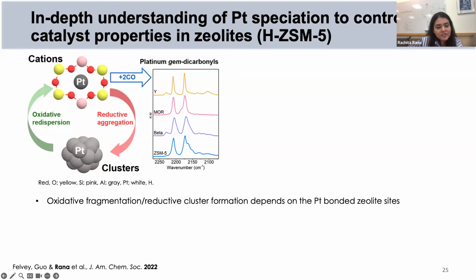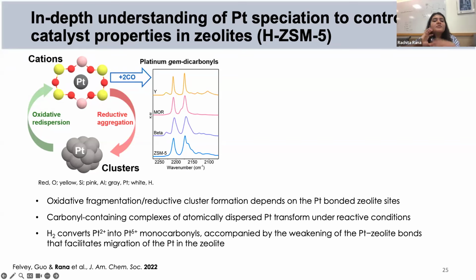Noah, his PhD student then, where they were trying to understand the speciation of platinum, where it would redisperse under oxidative conditions. And then when you reduce it, it would become a platinum cluster. And when it redispersed, the platinum would get into the pores of the material. And this was characterized using CO IR, infrared spectroscopy. You would see two carbon monoxide ligands being formed with the platinum atom that was in the pore.